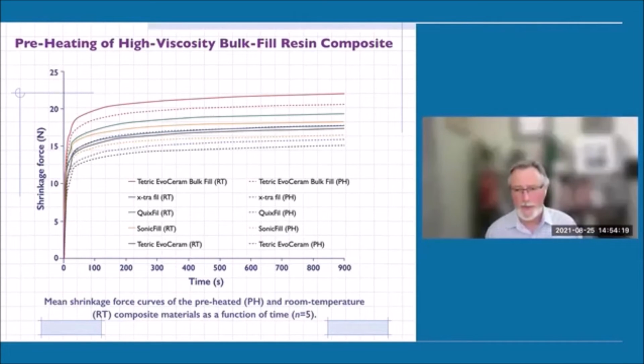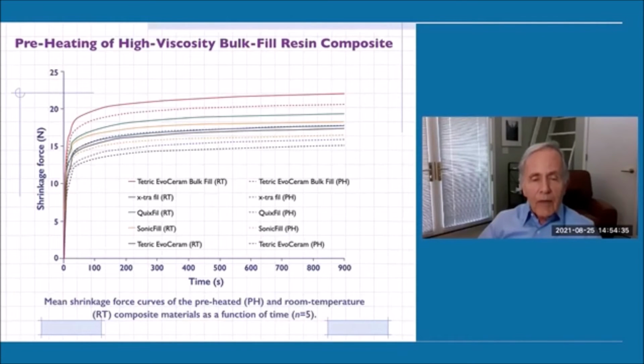Josh, you mentioned sonic fill, and it uses a vibratory mechanism to achieve flowing. Does it also have some of the other attributes of warming, like a higher degree of conversion, things like that? No, that's a good point, Larry. Sonic fill was just designed to flow better into a cavity and hopefully adapt to the cavity walls, but it doesn't provide the advantages of heating, which also provides better flow, but provides greater depth of cure, greater monomer conversion, and as we see, less shrinkage and shrinkage stress.